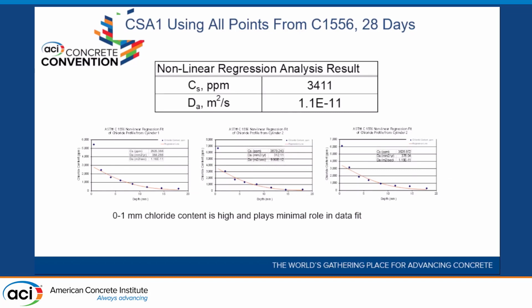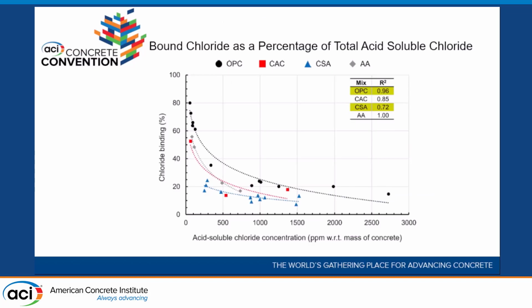Looking at CSA1, we had a higher diffusion coefficient. We're not doing anything artificial here. This is just taking the material that's been cured in a fog room, so there's nothing to leach out, and they're put into salt water on top of them. So this is what it's going to see in the real environment. We're not guessing on what type of pore water to put around there or anything else. But once again, fairly nice curves at this point.